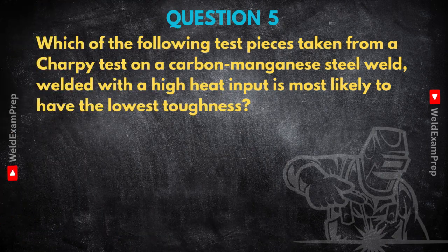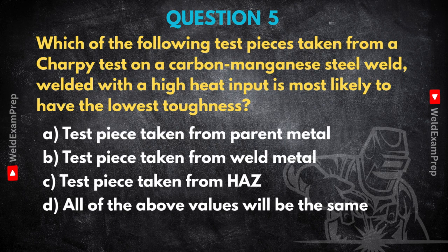This one brings together material science and welding parameters. Question 5. Which of the following test pieces taken from a Charpy test on a carbon-manganese steel weld, welded with a high heat input, is most likely to have the lowest toughness? Options: A, parent metal, B, weld metal, C, HAZ, D, all the same. Key things: high heat input and carbon-manganese steel.